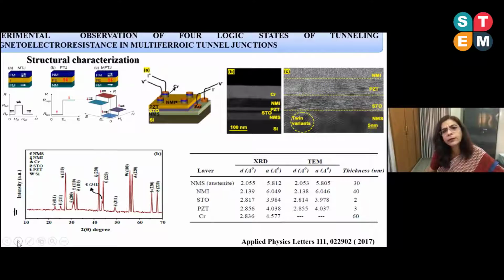In another work, we have tried to observe the four logic states of tunneling magnetoelectroresistance in this heterostructure, which was made up of two different ferromagnetic shape memory alloys: nickel manganese antimony and nickel manganese indium. In between, there was a layer of strontium titanate dielectric layer of 2 nanometers and a piezo layer of 3 nanometers.